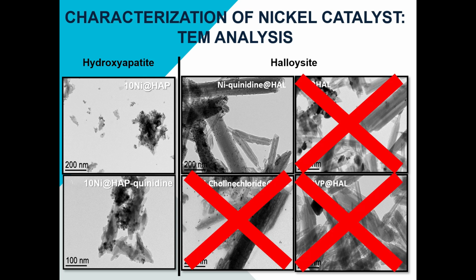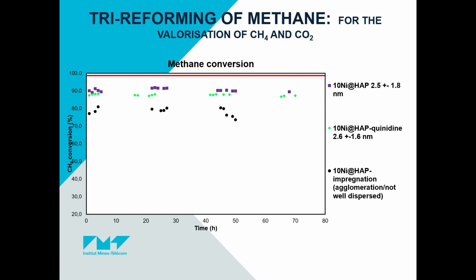Besides, the ICP analysis confirmed that the nickel was indeed properly adsorbed. In the case of hydroxyapatite, the same support could act as a stabilizer, giving similar results to the quinidine-stabilized particles. On the production of syngas, an initial screening is being performed.